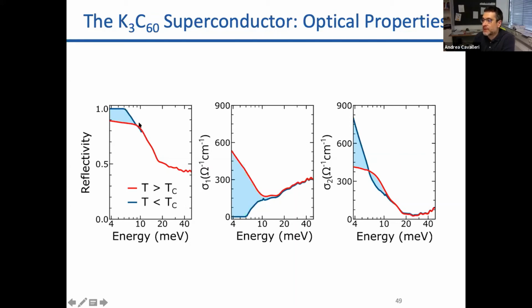When a material, which is a metal, which in this case is the C60 superconductor, which has metallic optical features at temperature above Tc, becomes a superconductor, what one obtains is a situation in which the reflectivity, the reflection coefficient, becomes exactly 1 all the way to the superconducting gap. The real part of the optical conductivity has a delta function at 0 frequency, which I don't see here, but has a gap, which now you can see in equilibrium when I cool the material below Tc, all the way to the gap 2 delta.